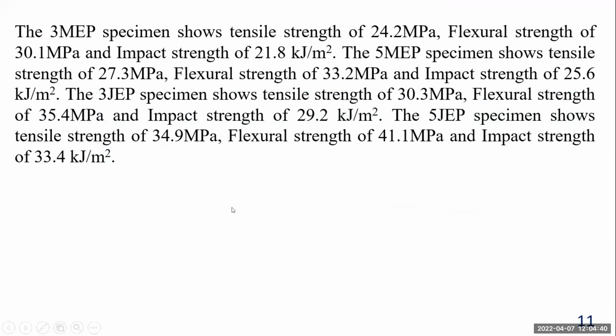As a result, the 3% Munja fiber epoxy specimen shows a tensile strength of 24.2 megapascal, a flexural strength of 30.1 megapascal, and an impact strength of 21.8 kilojoule per meter square. Similarly, the 5% Munja fiber epoxy specimen shows a tensile strength of 27.3 megapascal, flexural strength of 33.2 megapascal, and impact strength of 25.6.